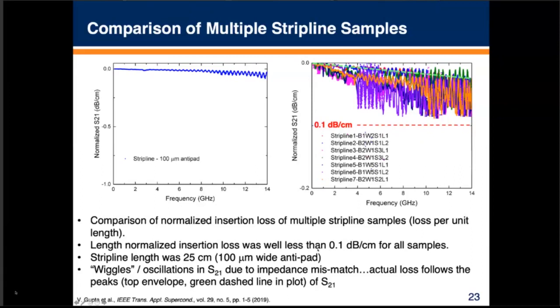We did do a little bit of modeling to verify that small amount of mismatch is contributing to those wiggles. On the top here, you can see this little green dashed line. That's the top envelope of those traces, where you're matched well and your signal makes it through. You don't have a resonance at that point. So that's more like the actual performance if you were to get essentially perfect matching for these structures.